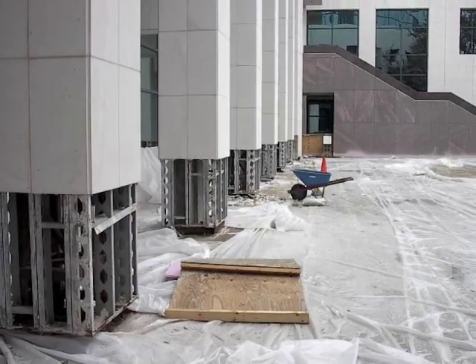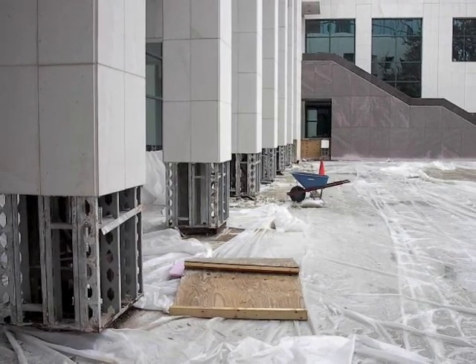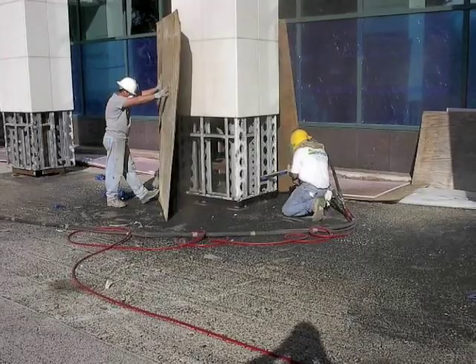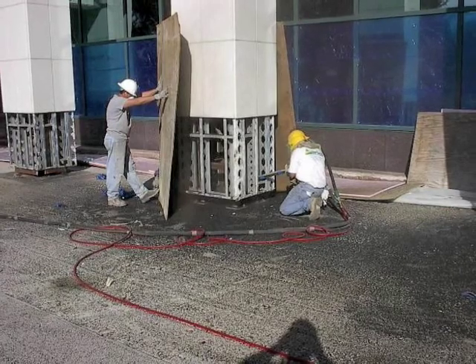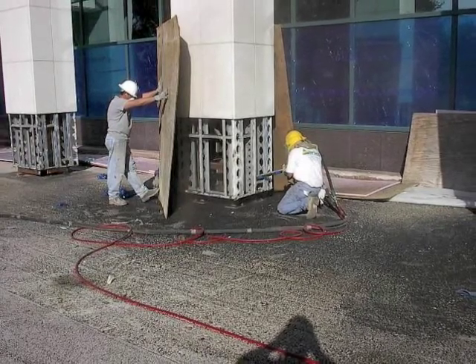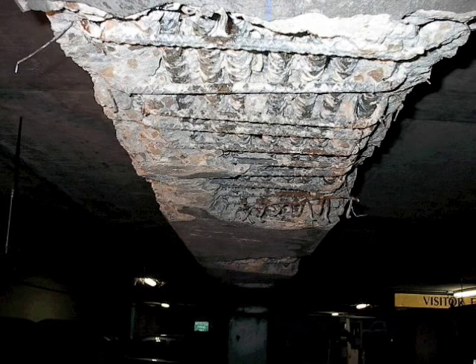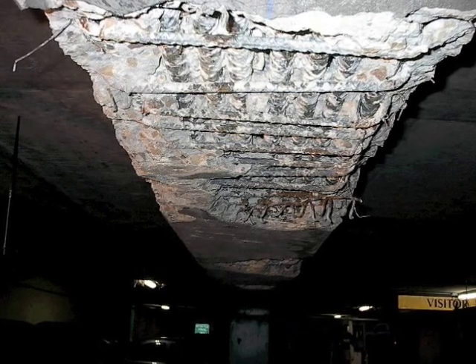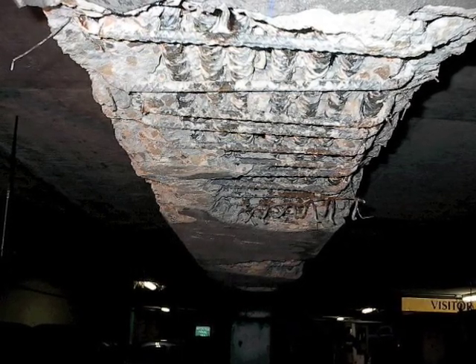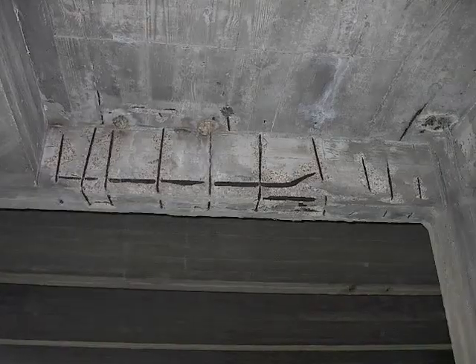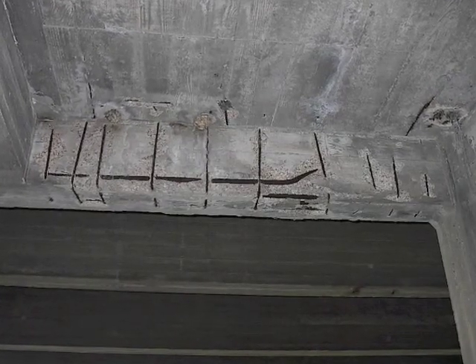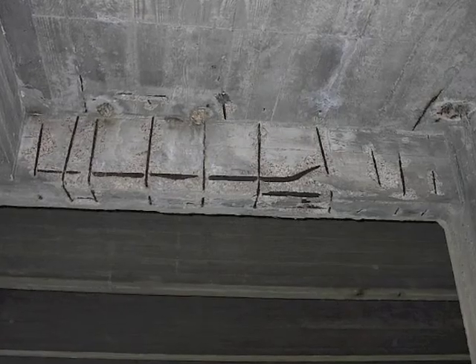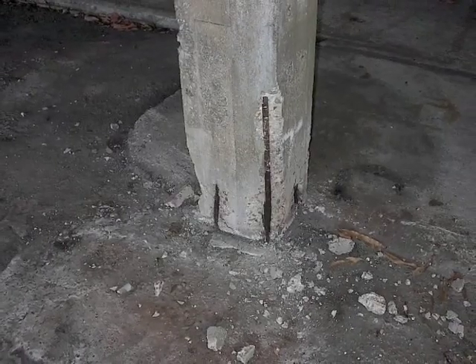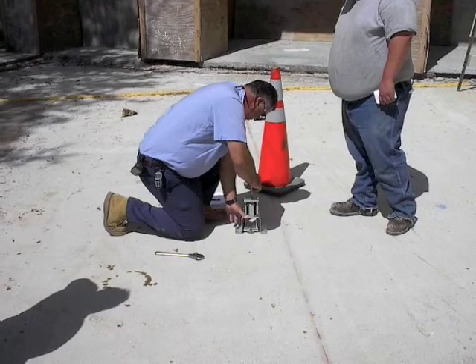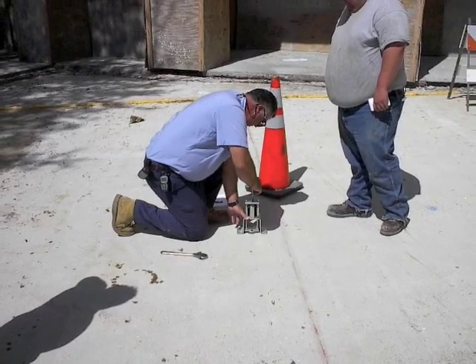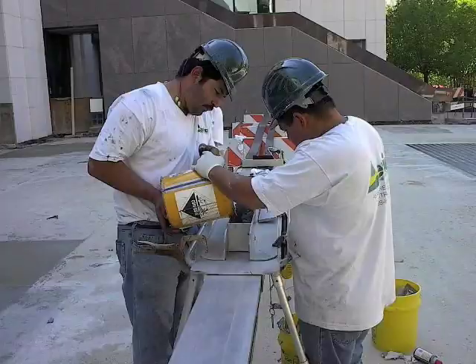Column and beam repairs above and below deck were also necessary prior to moving forward with the CFRP. First, above ground, we had to excavate the base of each column to install our waterproofing material. Here you see concrete beams below deck inside the parking garage, which were also in a severe state of corrosion, and we followed the same method as the concrete repairs. As we said before, we excavate to expose the steel, sandblast, apply anti-corrosive, frame, and repour with fresh concrete. Here we're testing the concrete prior to moving forward with the CFRP process.